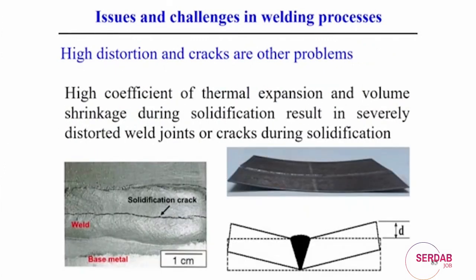In the final welded structure, even in fusion welding processes, high distortion and cracks are other problems. The distortion mainly comes from the coefficient of thermal expansion, and it happens during solidification: after application of the heat, the molten metal becomes solidified, and solidification cracking may also occur. That solidification cracking is mainly due to a large change in volume, or basically very high volume shrinkage during solidification. That actually creates either solidification cracking or a large amount of distortion in the final weld structures.